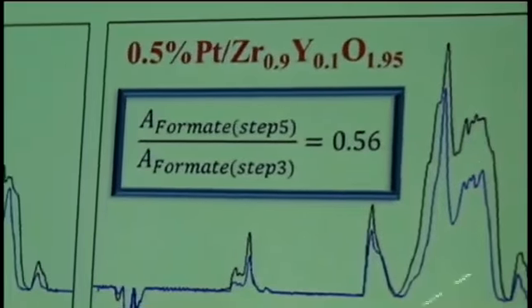And if we carry out steaming for a specific set time, and then we compare the catalysts, we did see that there was a greater fraction of formate from the initial that reacted on the yttrium-doped catalyst relative to the other.